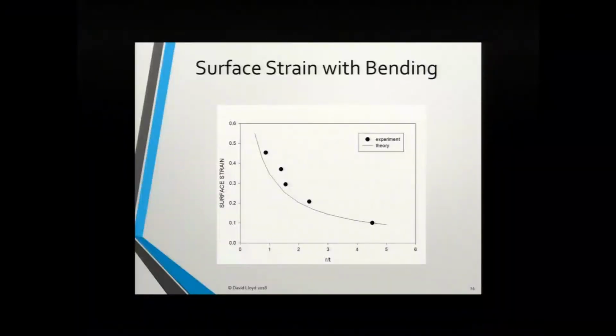And for that, we measured the maximum strain 10 microns below the surface. And this is what that data tells you. Again, the theory is a bit off from the experimental data. The experimental data tends to be above the theory, but the difference is probably pretty minor. I normally don't worry about that difference. So we've been quite comfortable using the theoretical mechanics equation for estimating the surface strains. But you can see that the theory does underestimate what the surface strain is.